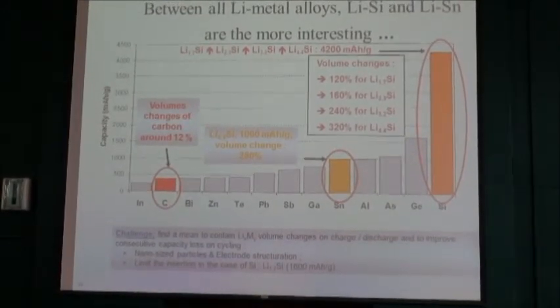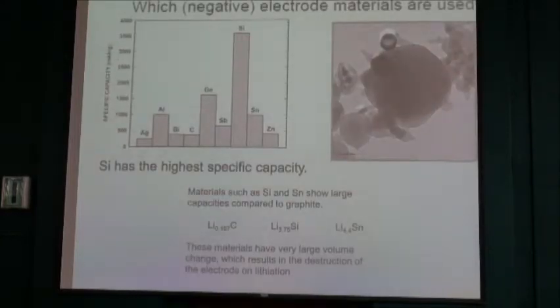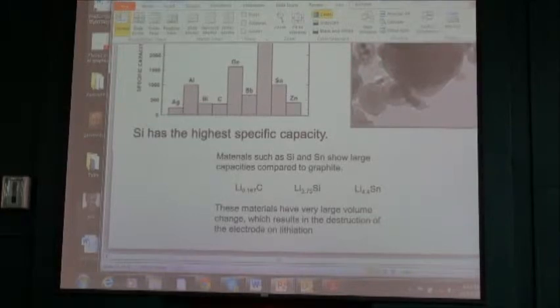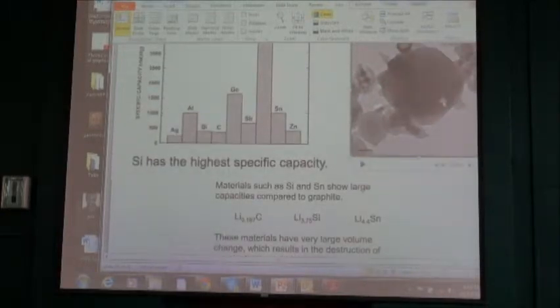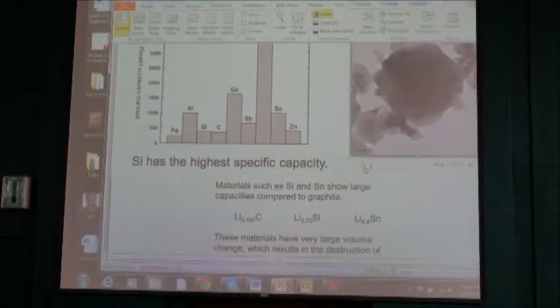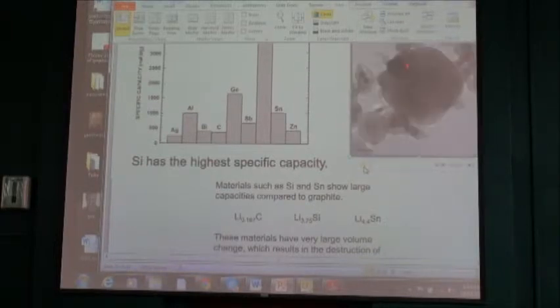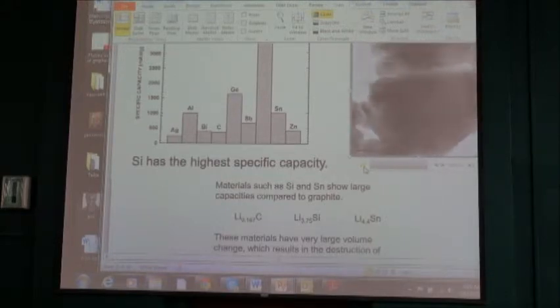Actually I can show you this one. This is an in situ experiment people did. Look, this is a silicon nanoparticle. Now lithium is coming in. You can see lithium is coming in. This is expanding, and then see, it's just breaking apart. This is a very nice experiment, done inside a transmission electron microscope. See, lithium is coming in, it is expanding, and eventually it just explodes. That's why we cannot use silicon in this form. You can see it nicely, right? But with graphite, if you do this, nothing happens. It's a very small experiment, but for silicon, that's a big problem.